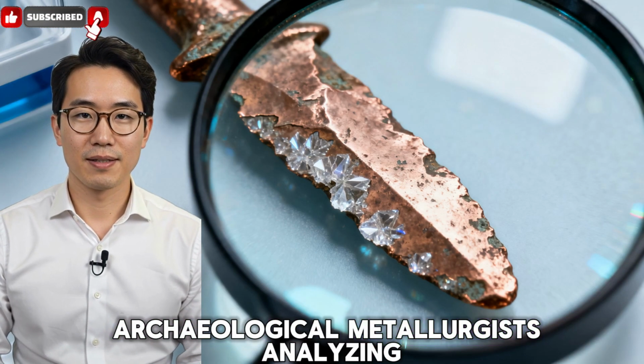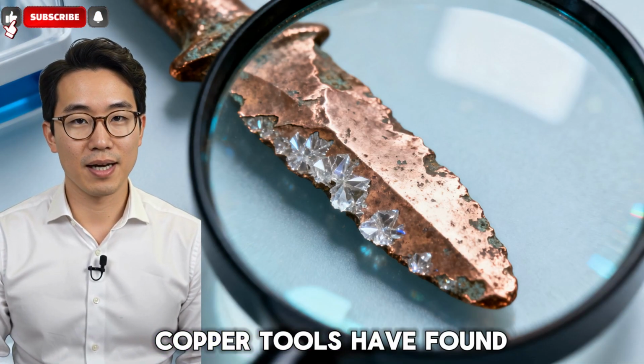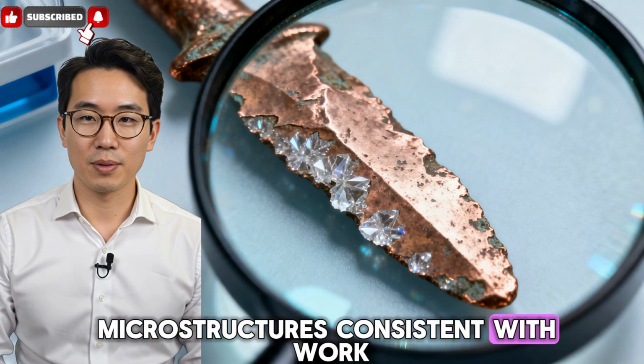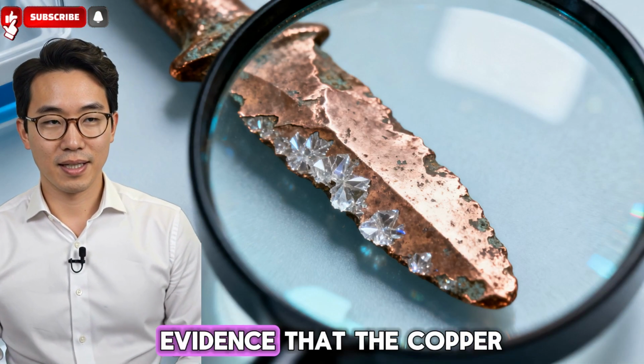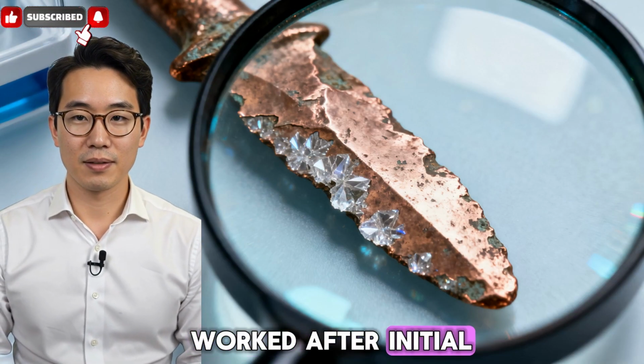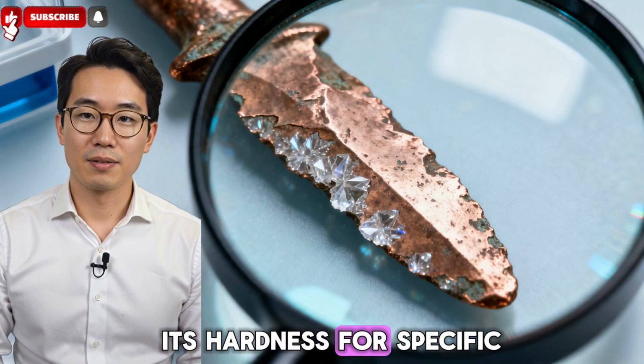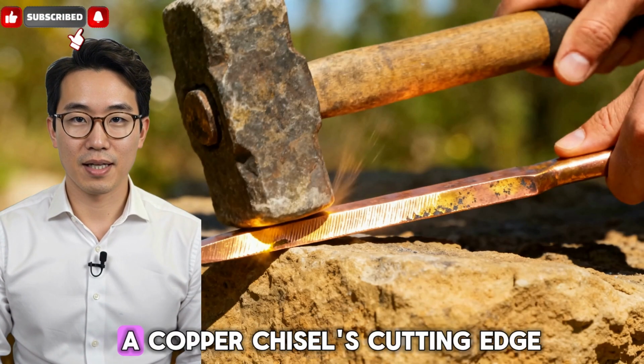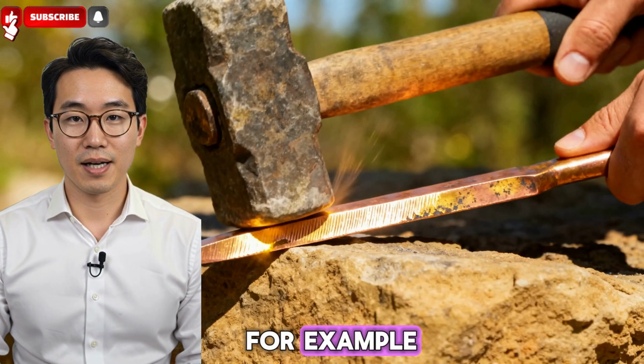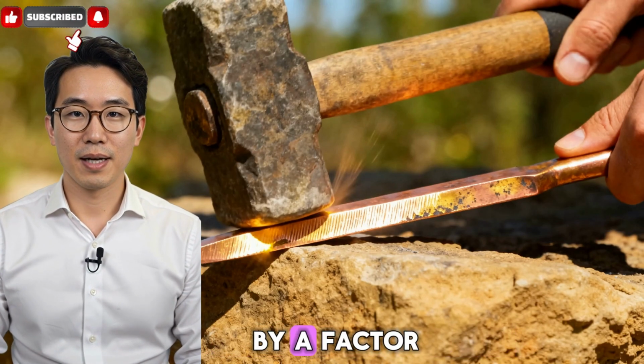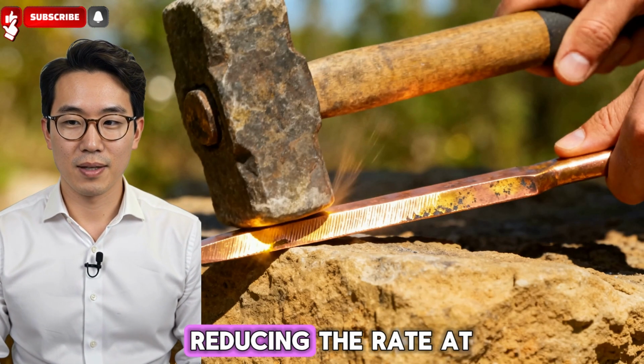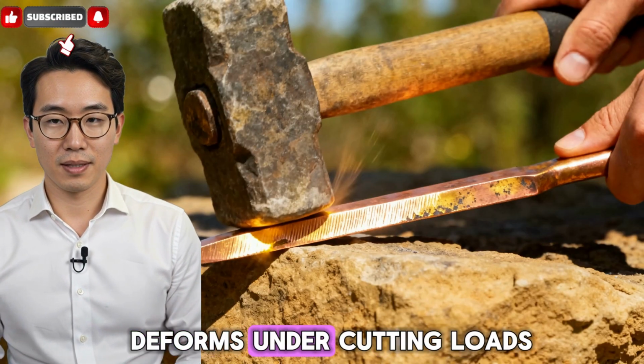Archaeological metallurgists, analyzing Old Kingdom copper tools, have found microstructures consistent with work hardening in some examples, evidence that the copper was repeatedly worked after initial fabrication to increase its hardness for specific applications. Hammering a copper chisel's cutting edge, for example, can increase the hardness of the edge zone by a factor of 2 or more, reducing the rate at which the edge deforms under cutting loads.